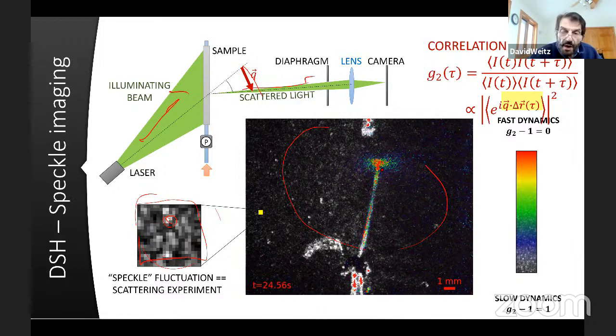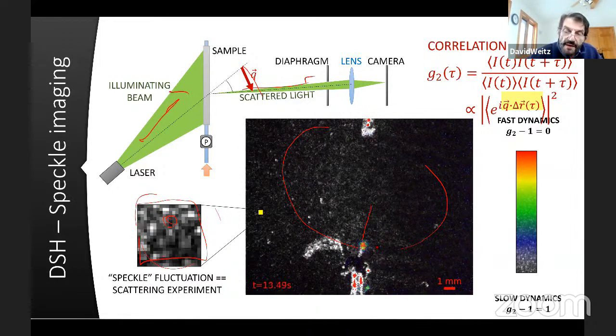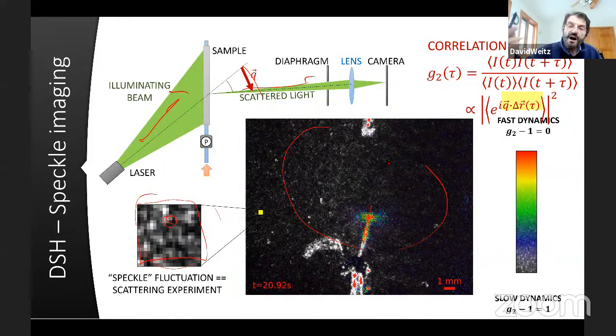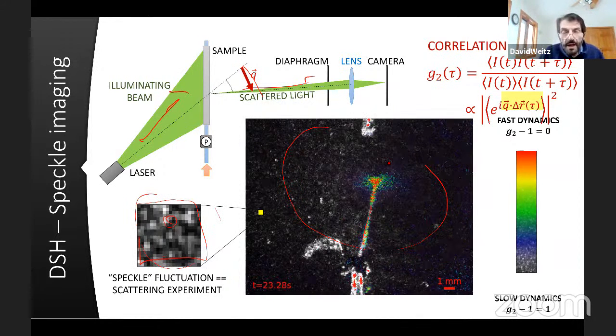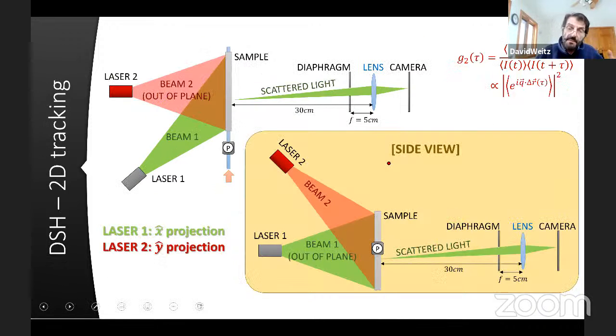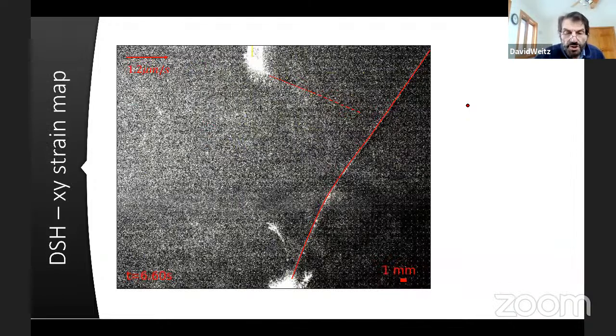And you can see now it becomes very clear that the strain field extends far away from where the crack is. You can use a second laser, or you use a beam splitter to do that. You can bring a second laser in, and you can have two lasers that will get a Q vector in one direction and a Q vector in a second direction. So you can measure motion in both directions simultaneously. And here's the same thing now showing motion in both directions.